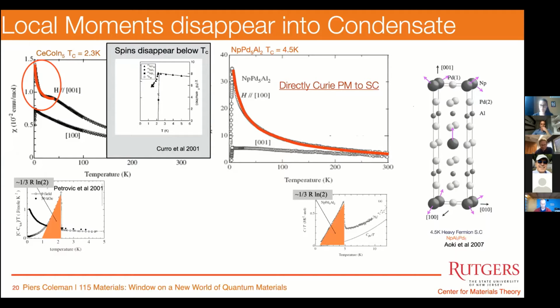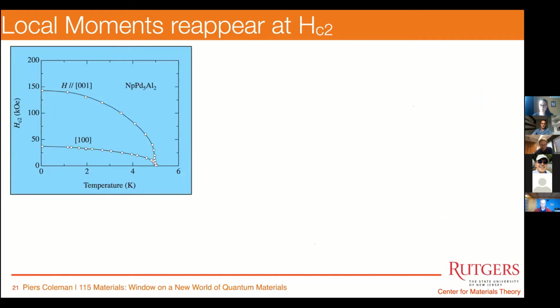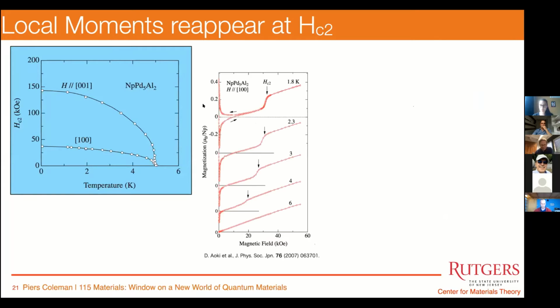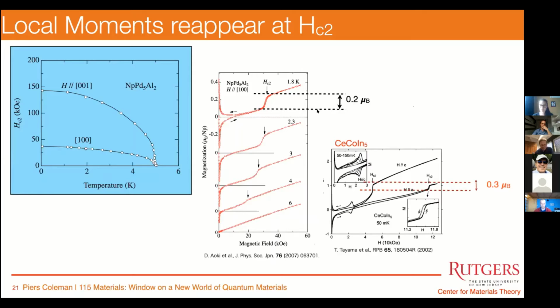You might think that those spins are still hanging around in the superconducting state, but they're not, because the Knight shift shows that the 1/T behavior seen at high temperatures disappears at low temperatures. So the local moments disappear into the condensate. And we know even more about this from the upper critical fields. Here is the upper critical field of the Neptunium system, and it shows this remarkable jump in magnetization at the upper critical field, which is a first order transition. And the jump is about 0.2 Bohr magnetons. Similarly, in the 115's at cerium cobalt indium 5, this jump is even bigger. It's 0.3 Bohr magnetons. This is this magnetic moment begins to be manifested inside the Q phase.